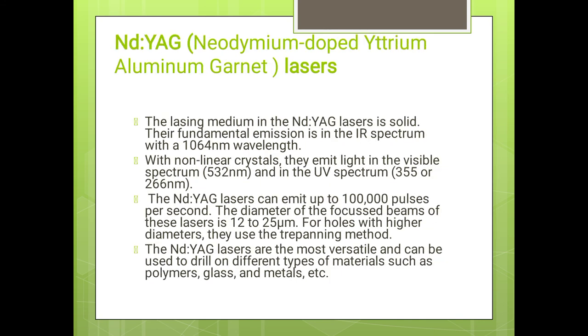Nd-YAG lasers. This is basically used when the base is a composite material, that means different types of base materials bonded together, and we are going to drill that. This laser will be used. It works at 10,000 pulses per second, at a 1064 nanometer wavelength. It can drill holes of 12 to 25 microns.